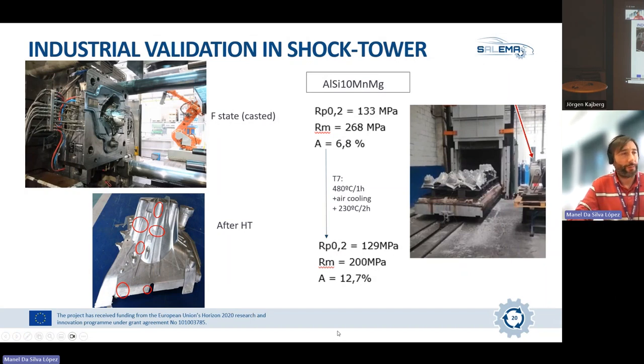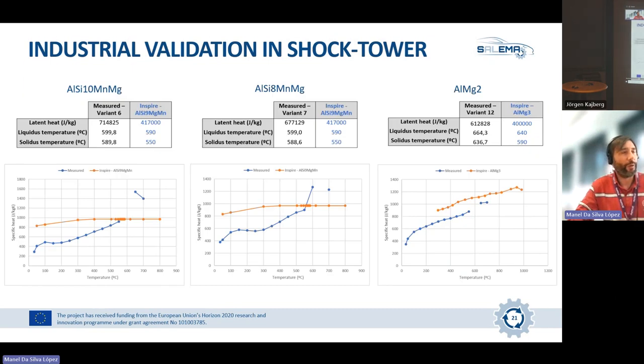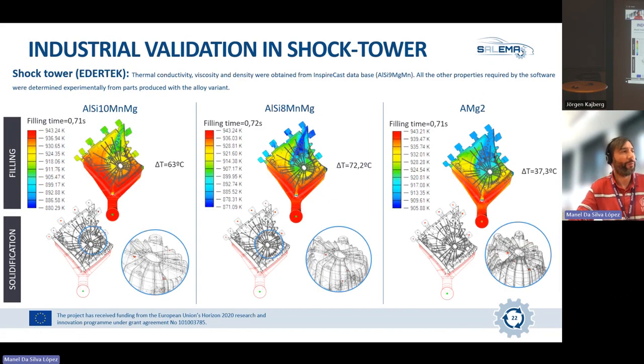Once we had this good result with the benchmark alloy, we moved on to adapt the production process to the new alloys. For that, the first thing we did was to characterize some physical and thermal properties required by the simulation software, in order to have experimental data to fit the simulation software that will provide us more reliable results than just the database data for the benchmark alloy, for the standard aluminum silicon 9 manganese magnesium or silicon 10 manganese magnesium. And with this data, we ran simulations.